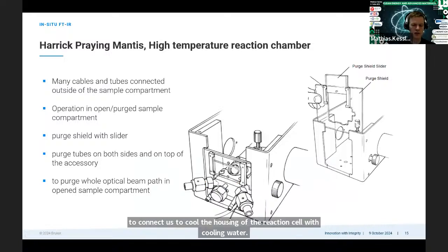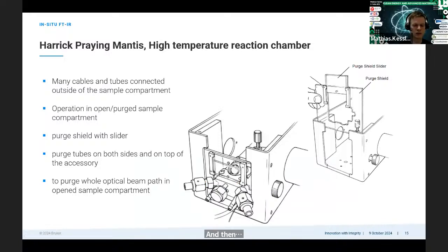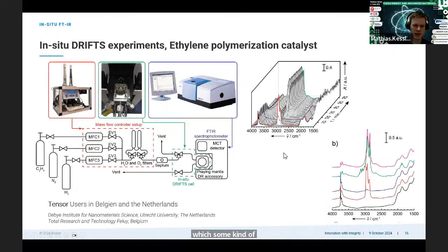And then to have the best sensitivity, we want to avoid contribution again of the lab atmosphere. Therefore, we can purge the accessory with dry air or with nitrogen gas. And also we can install a special front cover to the accessory, which limits the accessible openings. And therefore we have a very good purge condition if we use then the reaction chamber with some kind of a purge shield and a purge shield slider. And I want to give you some examples, some measurements from the lab.